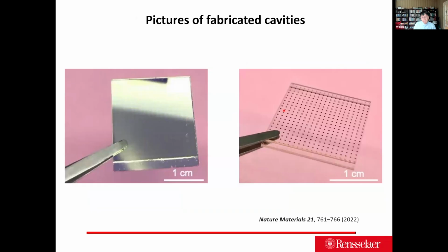And these are the samples we make. You can see the cavity is really homogeneous, and this is without the DBR, just to see the gold pad bonding together. And this is my student holding a tweezer. This is 1 centimeter in size. We apply a perovskite solution there and let it run into these nano cavities.